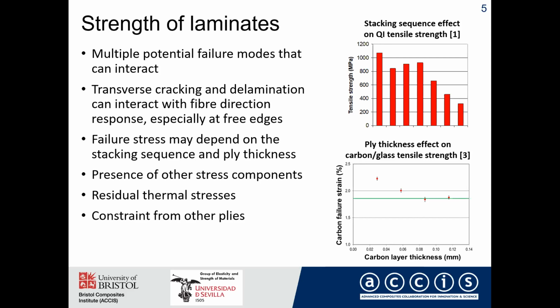The presence of other stress components, clearly in a laminate, if the laminate is subject to unidirectional loading, then you've got other stress components in the plies, you've got residual thermal stresses, and you've also got constraint from the other plies. And all of these can affect the strength of that laminate. And as an example, on the bottom right are some results for some carbon glass hybrid laminates, which shows that as the carbon ply gets very thin, the constraint of the adjacent glass plies leads to an increase in the carbon failure strain, quite considerable, from about 1.8 up to about 2.2%. So those sorts of effects mean it's very difficult to talk about strength of a laminate because it will depend on so many different parameters.